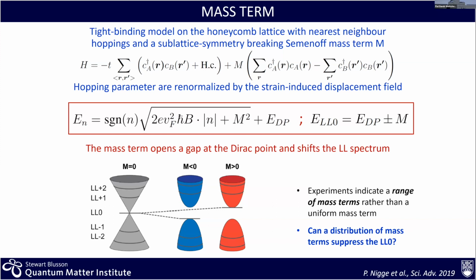Compared to what we heard today, one caveat here is this is not a real magnetic field. This is a pseudomagnetic field in that it doesn't break time reversal symmetry. And so the effect of M is the same on both K and K prime. This is something to be kept in mind.